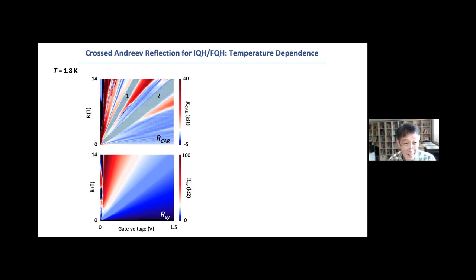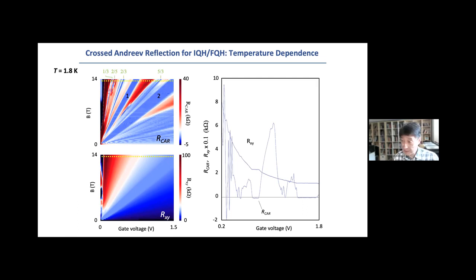But the more exciting part is that rather than only integers, you see that a lot of fractional CAR processes have already started to show up, right? So this is very encouraging. With this device, we already see that many of these fractional quantum Hall effects do appear as negative signals in R_CAR. A cross-section at the high magnetic field of 14 Tesla shows that R_XY has nice plateaus corresponding to all the quantum Hall sequences, including 1 and 2, but more importantly these fractions. And the fractions, as I just mentioned, show a large negative CAR value, which indicates that indeed CAR is very robust in the fractional quantum Hall states.